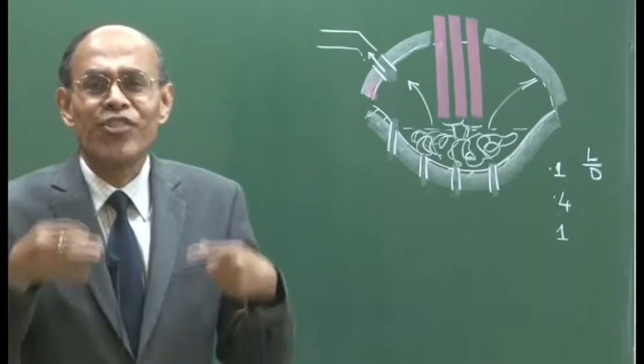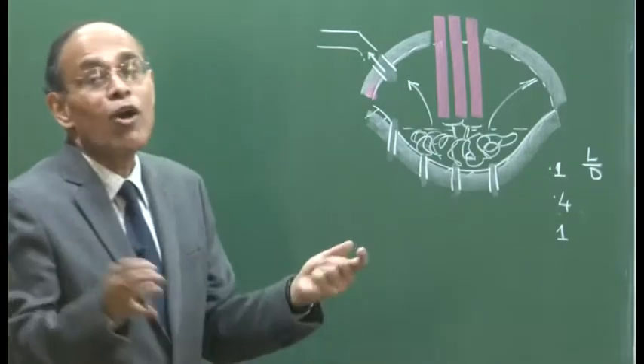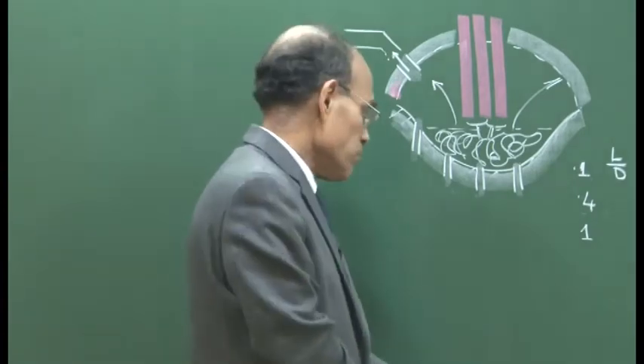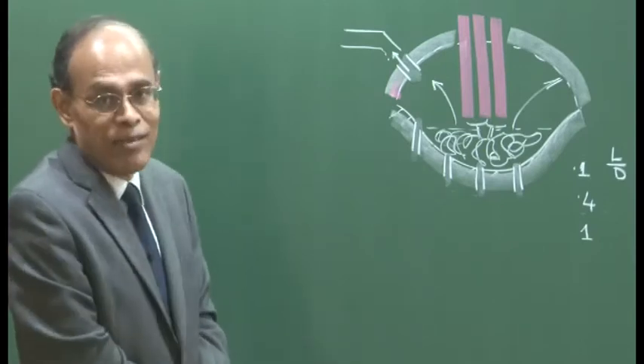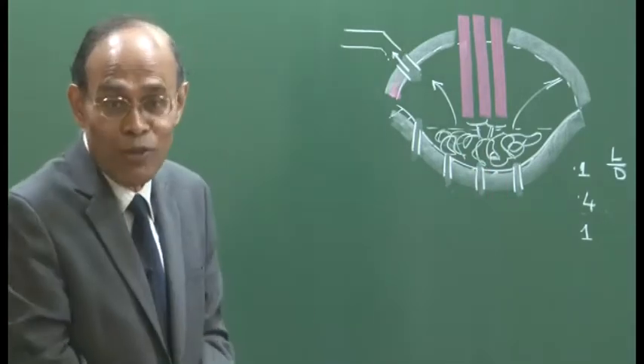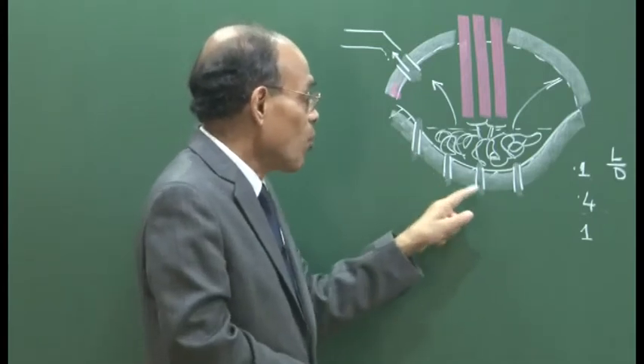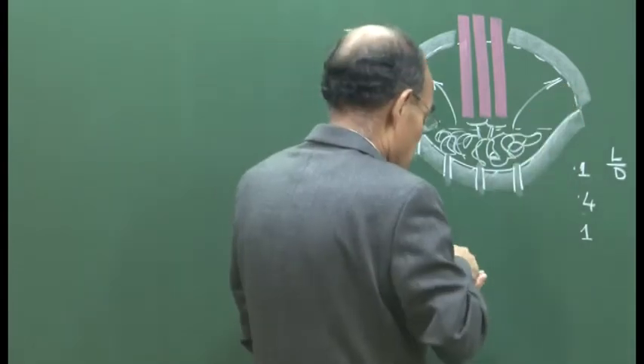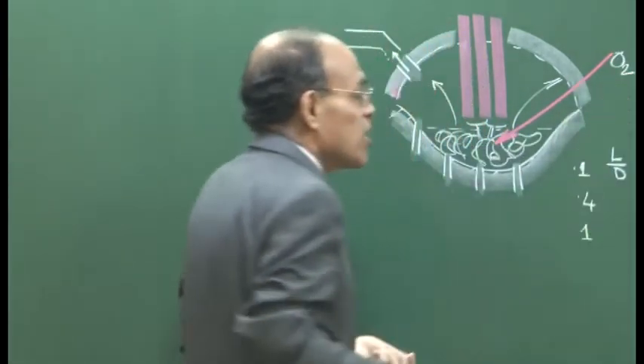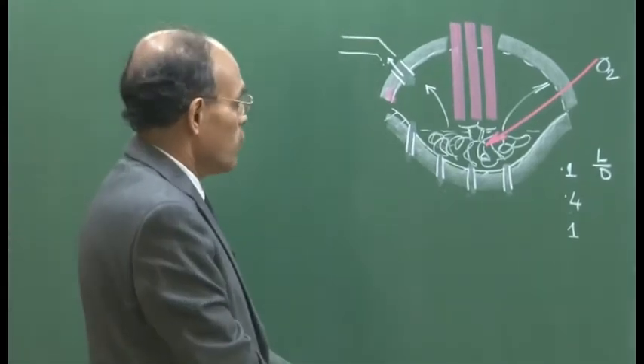That is the trend: people have realized they do not have to use a saucer geometry, and a BOF-type geometry can also work. That is why, in the same shell, people are blowing both oxygen and argon. This varies from plant to plant, so there is no generality. With the introduction of bottom stirring facilities and oxygen lancing in the furnace, one can dispense with the lower aspect ratio geometry, which helps expedite the reaction rate.